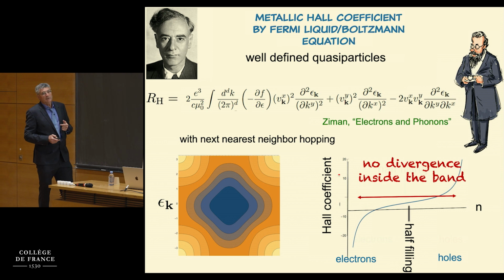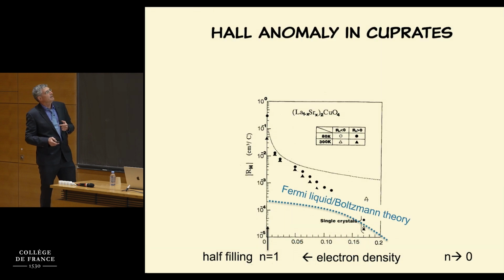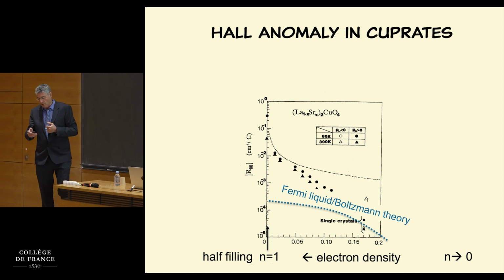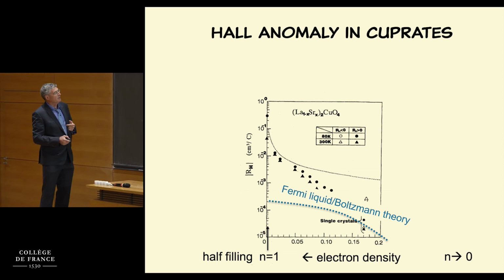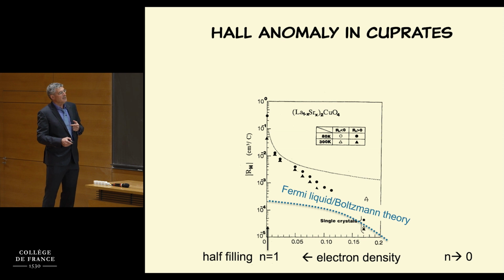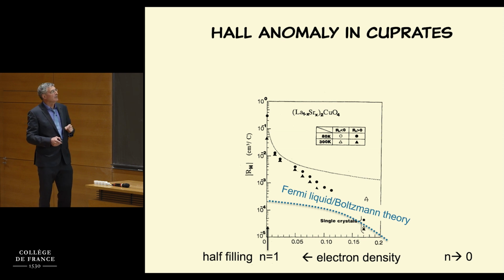Okay, so once we realize that, we look at the experiments. And this is experiments in doped lanthanum strontium copper oxide. One has to understand that people plot this curve such that the electron density goes from the right to the left. This is the density of 1 electron per site, so it's half filling. As I said before, in the tight binding model, nearest neighbor, the Hall effect should vanish here smoothly, just go through 0. But the experiments show that it diverges with a positive number.